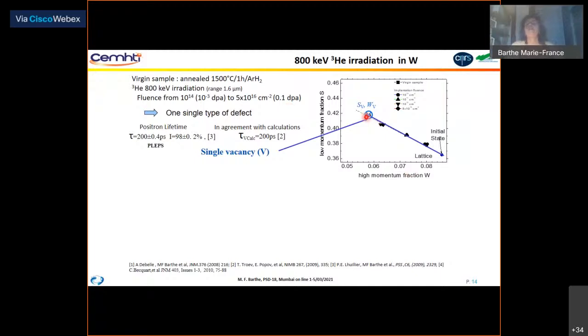And we have seen that S and W values are aligned on the same straight line. We measure the lifetime for the sample irradiated at the highest fluence. We obtain 200 picoseconds, which is the lifetime expected from theoretical calculations, DFT.